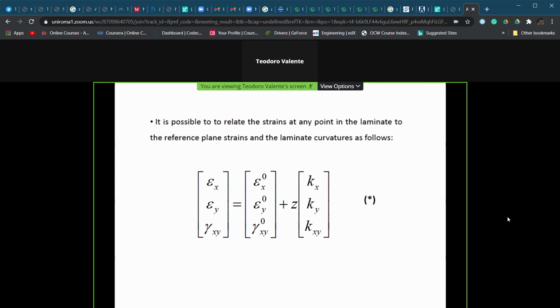And the general approach puts in relationship the values of the strain inside the laminate to those which are referred to the reference plane strains, together with the terms linked to the so-called curvature tensor. Z is instead the z-axis, so along the through thickness axis, this one, okay? And so this is the basic approach in terms of laminate when we put together different lamina.